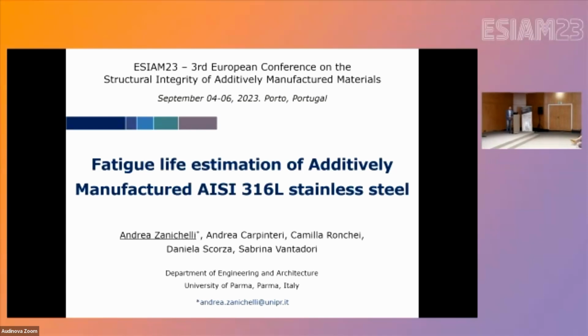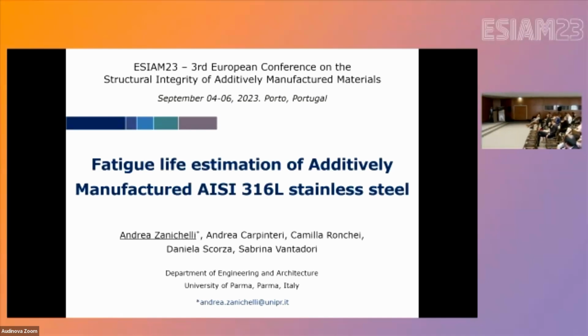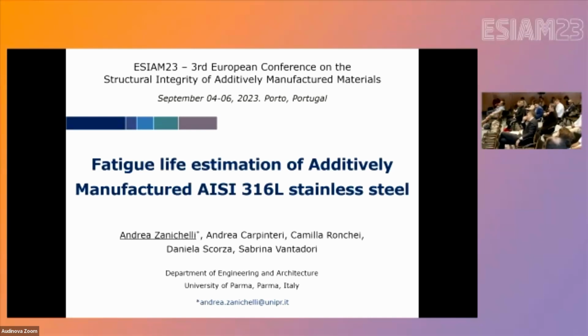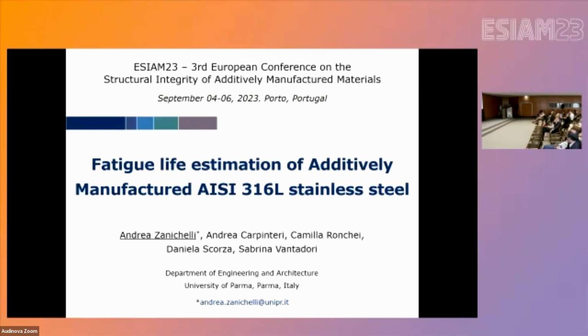It's necessary to comment on this approach because this approach is appropriate for a material like you selected, this 316L, because this material has parallel lifetime curves in tension and torsion also. In your approach, you use the conventional fatigue limit, but this ratio between tension and torsion is different in the lifetime region in different types of material, where these lines are not parallel. It is necessary to extend this approach to more general materials, not only this one, because this material seems to be conventional, but specific to additive manufacture is this non-conventional, not parallel line.